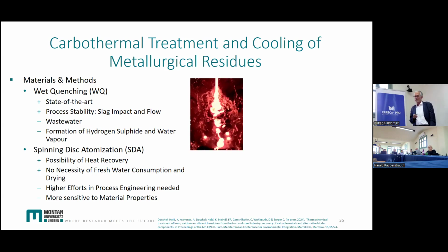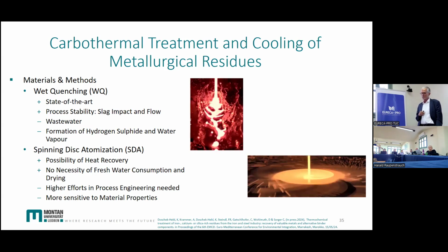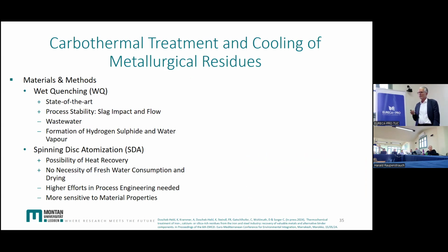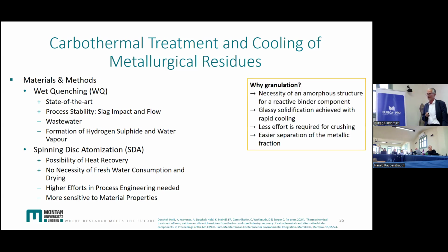Looks like that. Another way is spinning disk atomization. That means you produce hot air, and this can be used for heat recovery, and you don't need any fresh water. What is the disadvantage? It's more complicated. It needs higher efforts in process engineering, and it's more sensitive to material properties. The word slag is such a simple word for such a complex material, because as soon as you change the properties a little bit, or the temperature, the viscosity and everything changes dramatically. And this is important for this process.